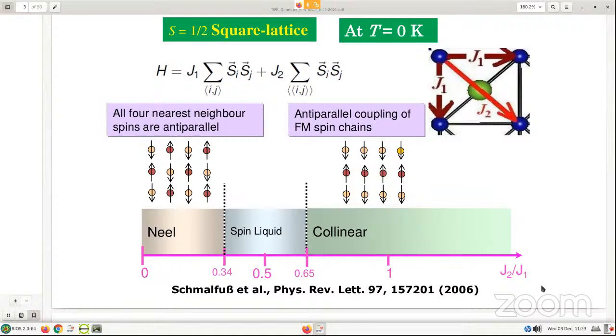In fact, if you notice, in all my compounds except one, copper is the magnetic element in those 4 compounds which I already listed. Now, this is the theoretical phase diagram, and depending upon the ratio of J2 by J1, the second neighbor interaction to the first neighbor interaction, you get different magnetic ground states. Obviously, when J2 is 0, that means only first nearest neighbor antiferromagnetic exchange interaction, you get the conventional Néel type antiferromagnet.